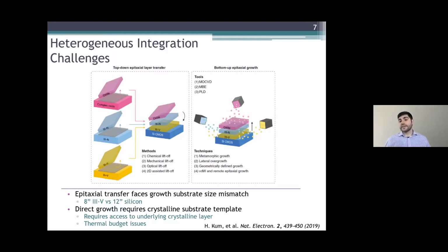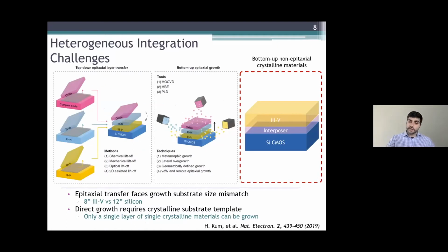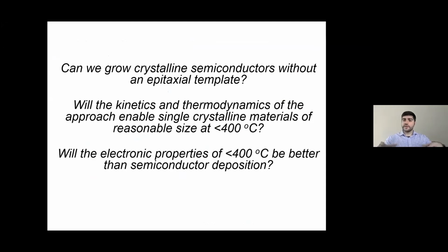The challenge with that is you only have access to one crystalline surface, and as you start to get more and more complex, it becomes almost prohibitive to take this approach. So what we're trying to do is put a new tool in the toolkit: bottom-up, non-epitaxial crystalline material growth. Where you have your silicon device, you might have some oxide or nitride interposer, you might have some interconnects, and on top of that you build local crystalline materials. We're focusing on III-Vs. To address this challenge, in this first part of the talk, we're going to talk about three main points.